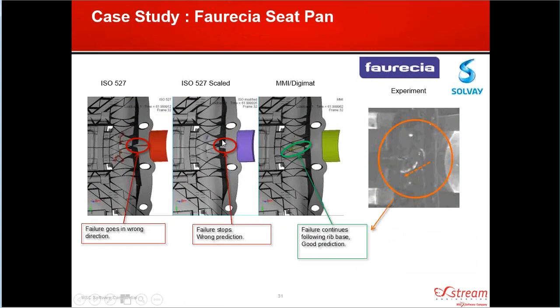In the final scenario, we're about to have a final failure of the part. If we look at the first approach, the isotropic approach, because of that initial failure we had, the transverse failure, now our failure is progressing in the wrong direction, moving away from the rib. So we're not going to be able to accurately predict the failure mode or the failure amount, the force at failure, of the part.